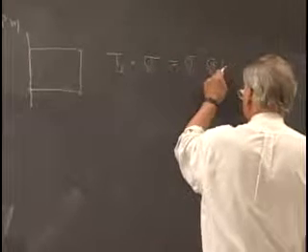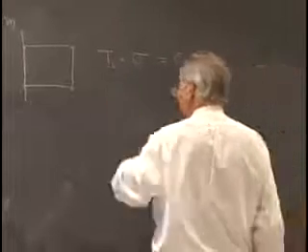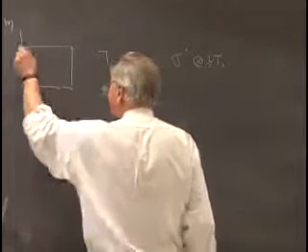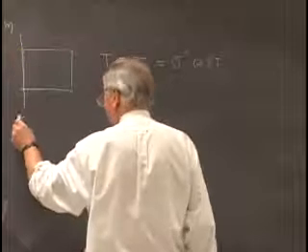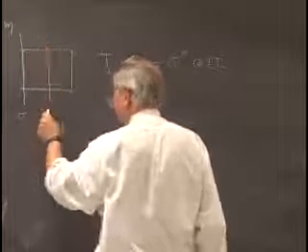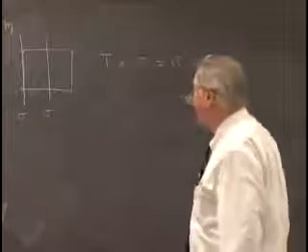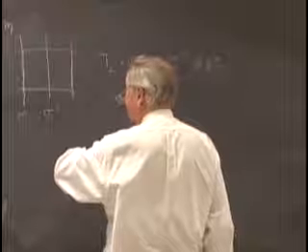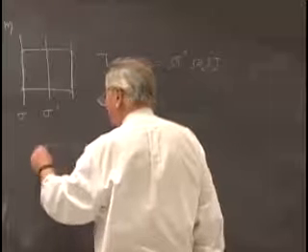We sketch that out and once and for all could decide that it's going to be a new reflection operation that's located halfway along this perpendicular translation. So this reflection operation sigma combined with this translation gave us a new reflection operation sigma prime halfway along the cell. And of course we have this one hanging at a lattice point as well. And then came the interesting one.